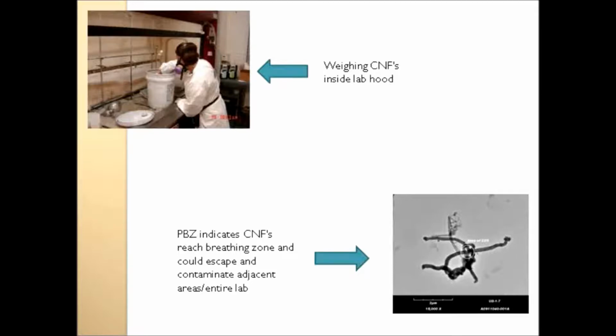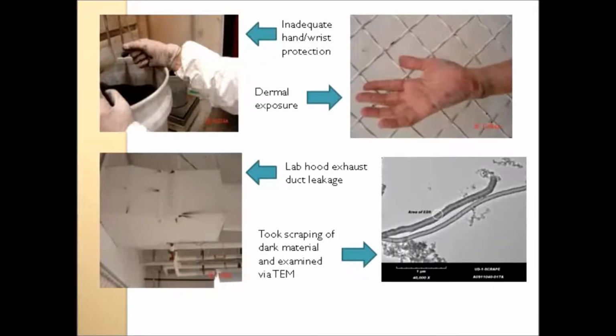This is another interesting finding that you really don't know about until you see it. It just strikes you when you're on site conducting these assessments. She was doing a very nice job of weighing out. She did use gloves. She did wear a Tyvek suit, so she's wearing all the right things. However, something like this happened where the sleeves started to ride up. And we spotted that, and I took a photo of that. And you can see right here the black showing on the wrist is due to the carbon nanofiber she was weighing out.